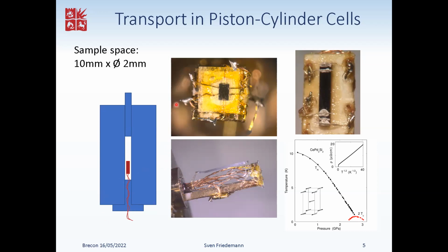And then inside the pressure cell, you've got a sample space about 10 millimeters long and 2 millimeters in diameter. And nevertheless, you can put these pressure cells into highest magnetic fields and into cryostats down to lowest temperatures. And hence you can conduct many experiments. So I've got here pictures of samples that have been mounted for resistance measurements or even for Hall effect measurements, where the sample is actually living on this end here. And this guarantees the orientation relative to the magnetic field. And these experiments have been very important.